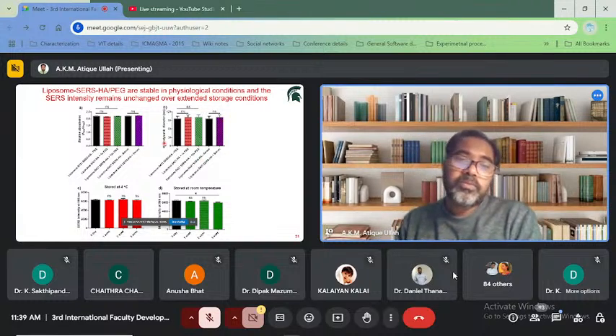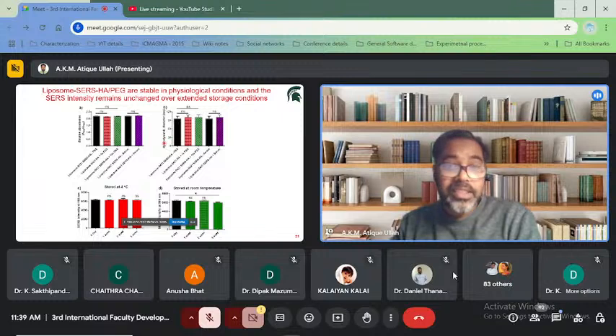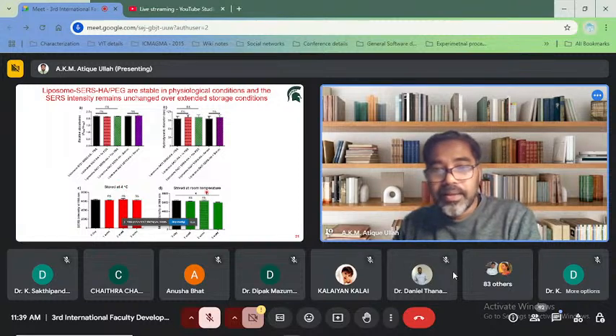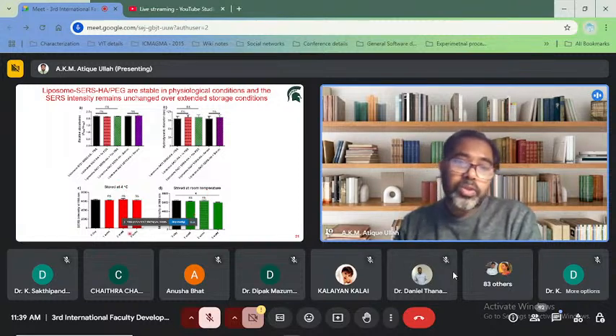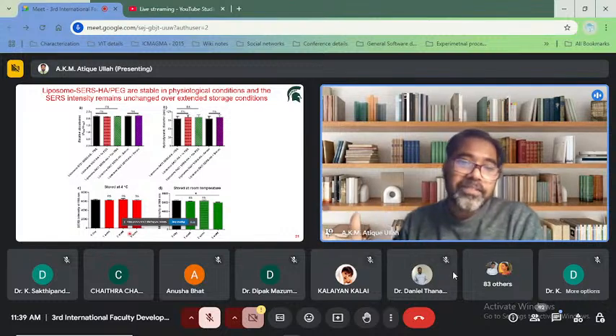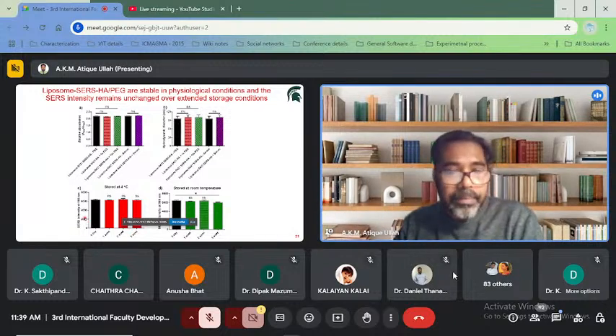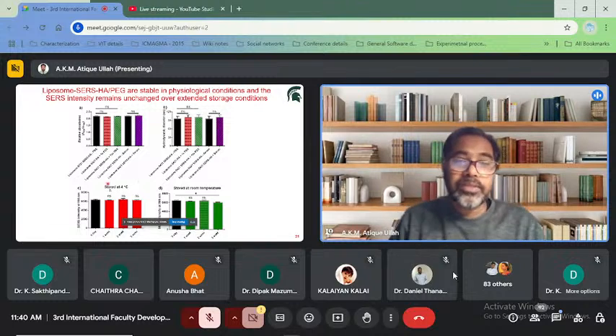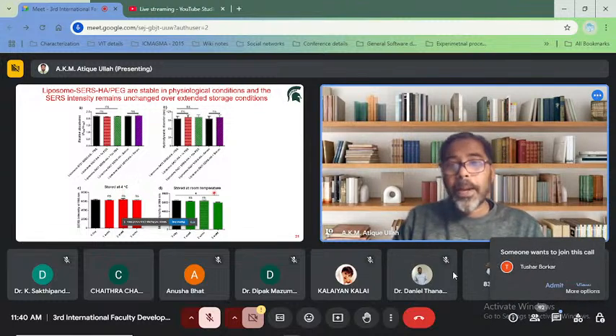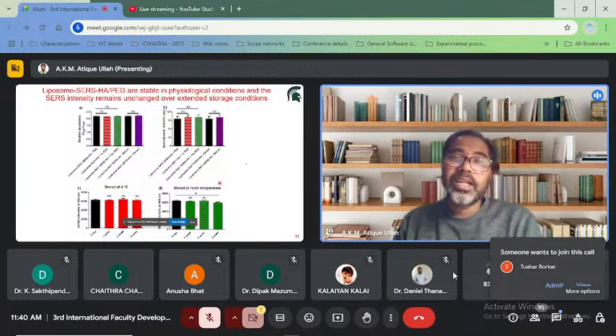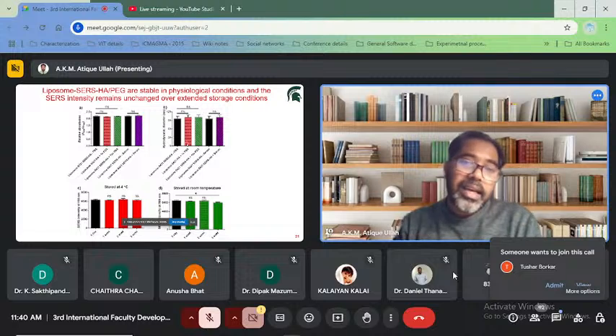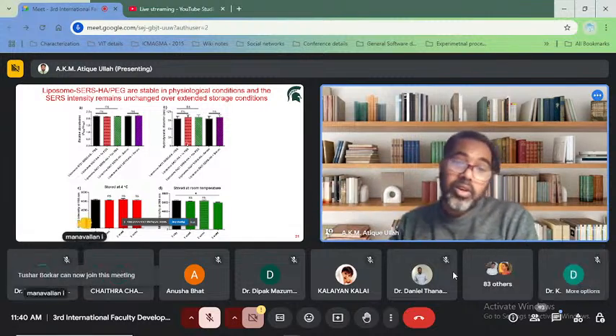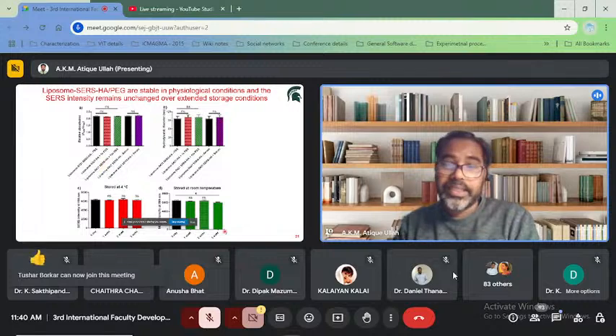We also examined the stability of the SERS nanoparticles in storage conditions. This is at 4 degrees centigrade and at room temperature. Over the 3 weeks, we found there is no significant change in the SERS intensity if the nanoparticles are stored at 4 degrees or even at room temperature. So from these experiments, we figured out that our SERS nanoparticles are stable in physiological conditions and storage conditions over at least the 3 weeks we examined.